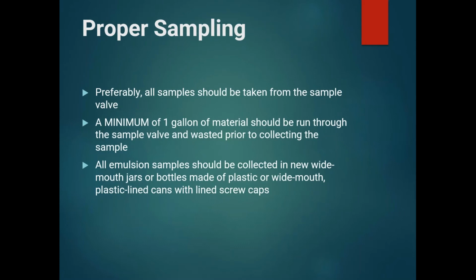When you do pull the sample, whether you're taking it from a valve or a spray bar, you want to make sure that a minimum of 1 gallon of material has run through that sample valve and been wasted before you begin collecting your sample. That's to ensure that you have no contamination in that sample from whatever's left in the valve last. And then all emulsion samples should be collected in new wide mouth jars or bottles made of plastic, or wide mouth plastic lined cans with lined screw caps.